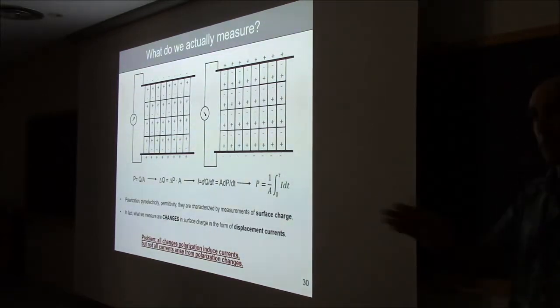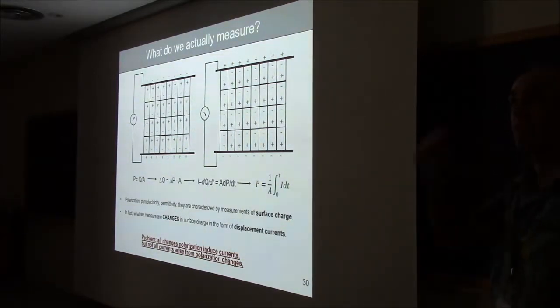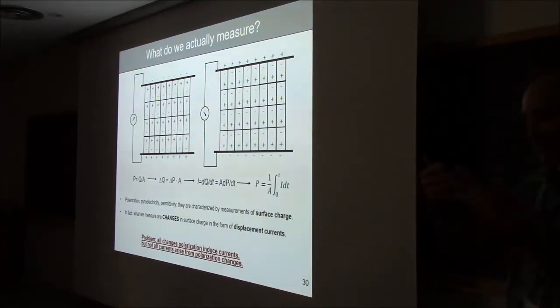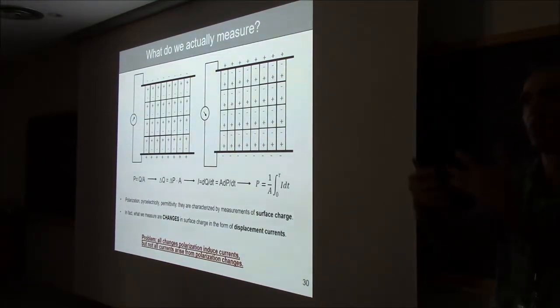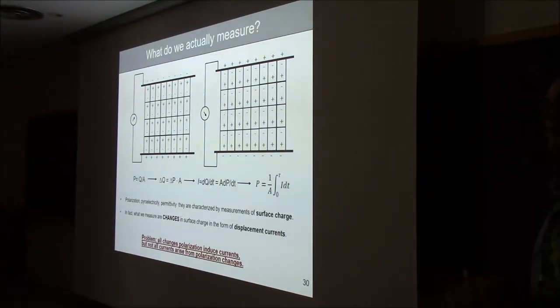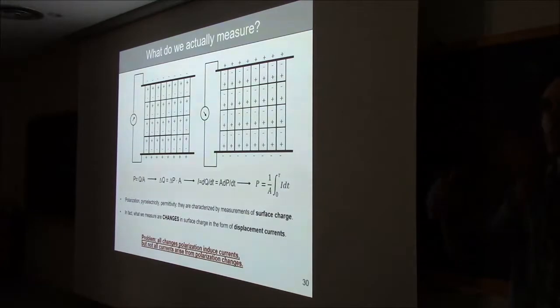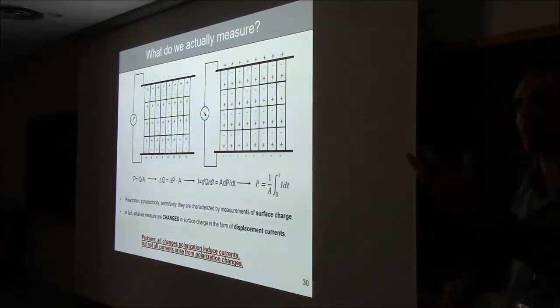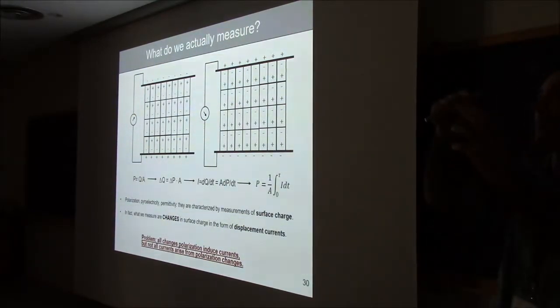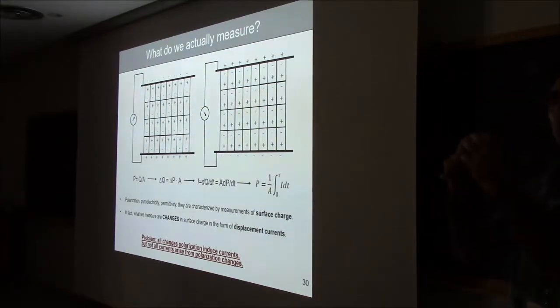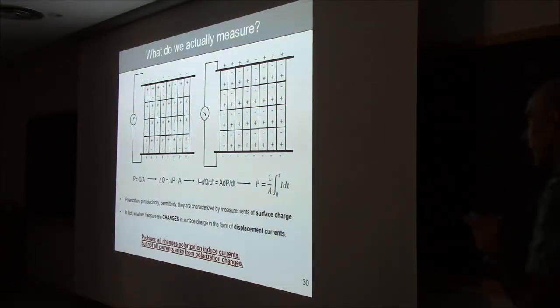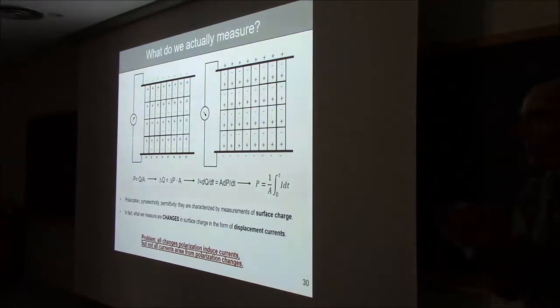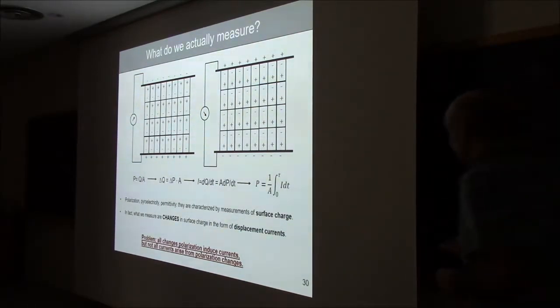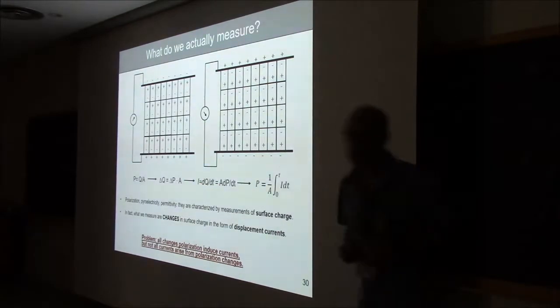I think, maybe David will correct me if I'm wrong, this is true even for theory. So to quantify polarization, you need to do it in reference to a lattice that is non-polar. Or if you do X-rays, you say, okay, these are the atomic positions, this gives me the polarization by comparing the atomic positions with respect to what would be the centrosymmetric lattice. Okay? I think that's true for theory. It's definitely true for experiments. You can only ever measure changes in polarization, which you measure in the form of currents.